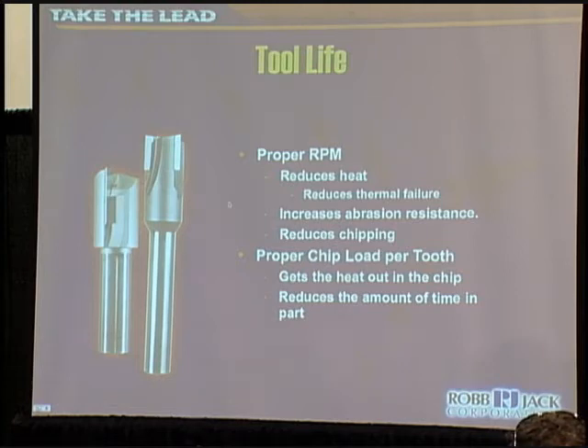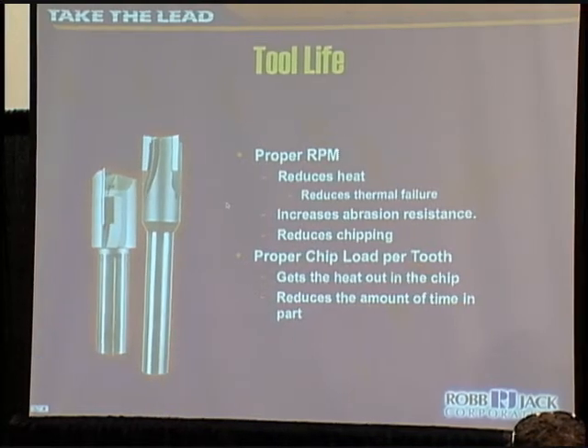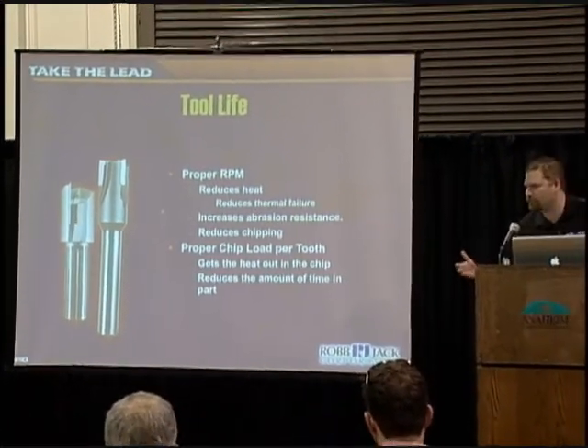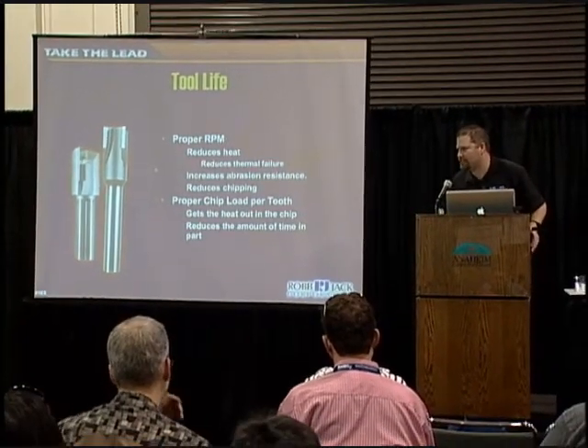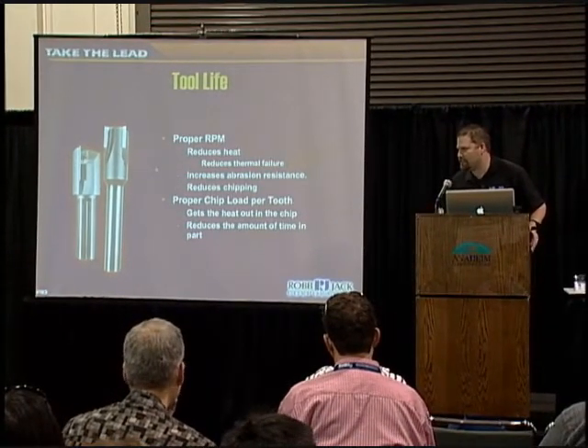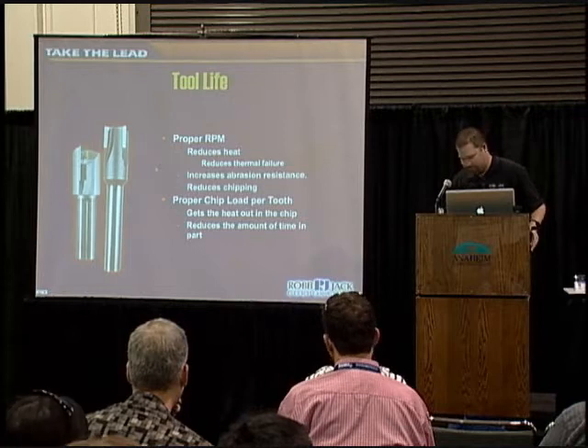For composites, depending on whether it's military or commercial aircraft or medical type things, typically surface footages range between 800 and 1,000 surface feet per minute. And you would interpolate a chip load of about 10 thousandths for a 1-inch tool. So a 1/2-inch tool, maybe in the 5 to 6 thousandths chip load, and you would interpolate down from there.